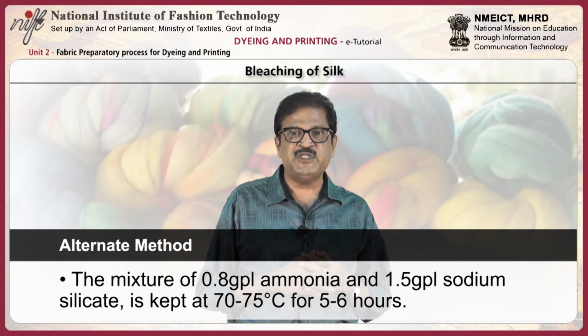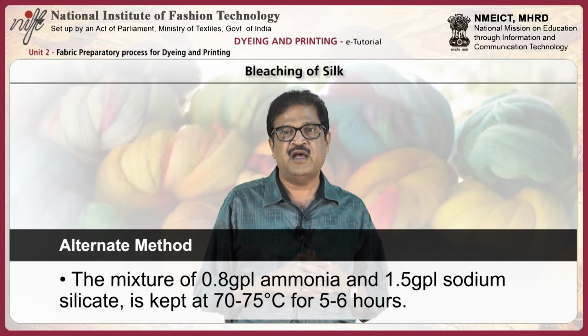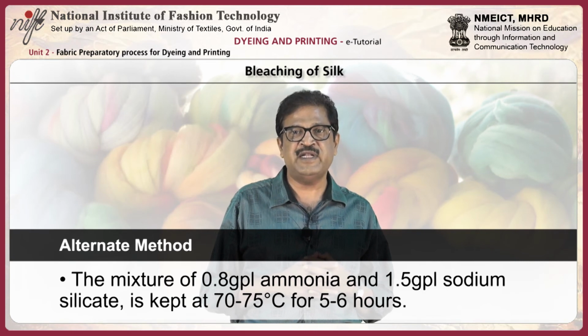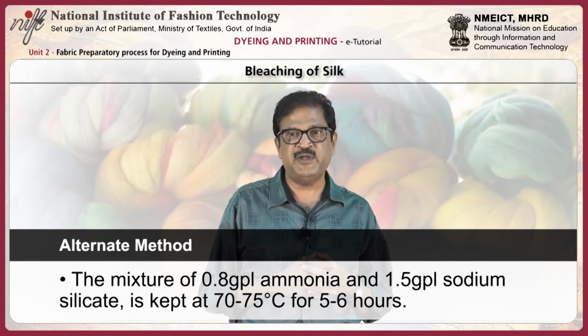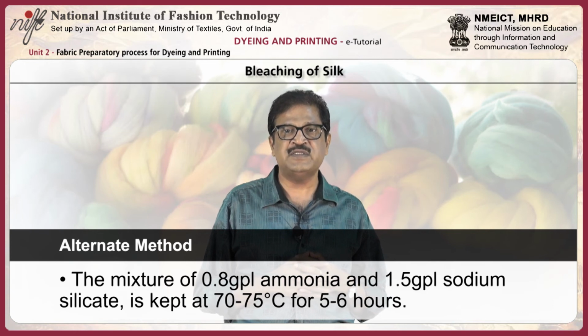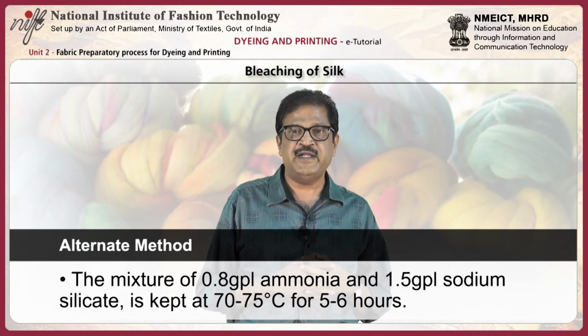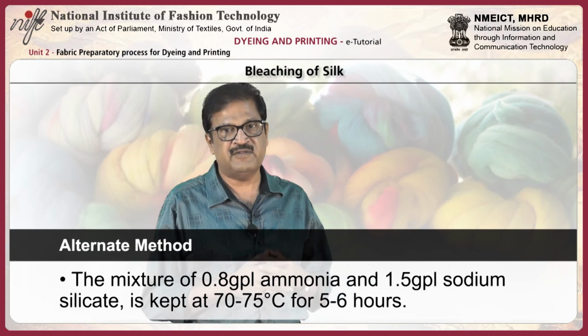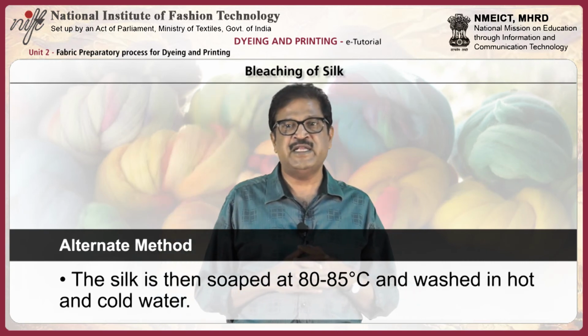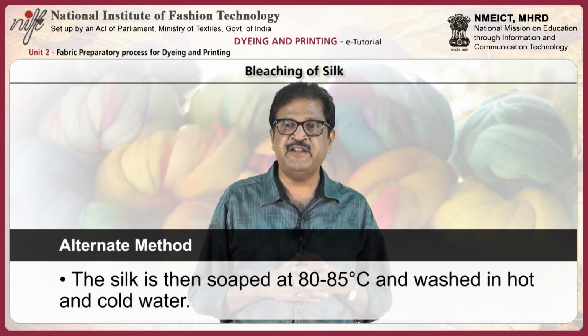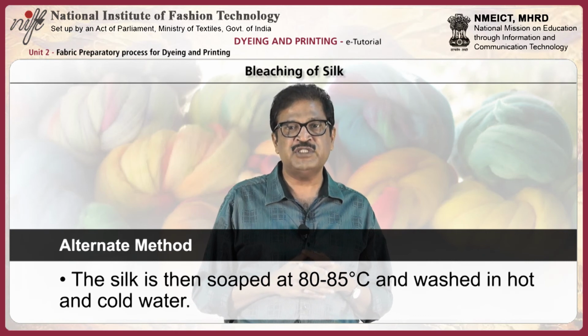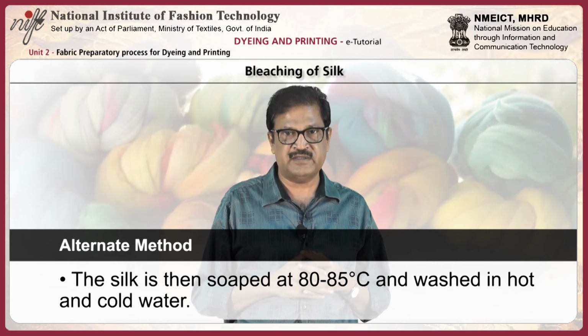Here the mixture of 0.8 grams per liter ammonia and 1.5 grams per liter sodium silicate is used. The temperature is kept at 70 to 75 degrees and time duration of 5 to 6 hours. The silk is then soaped at 80 to 85 degrees centigrade and washed in hot and cold water.